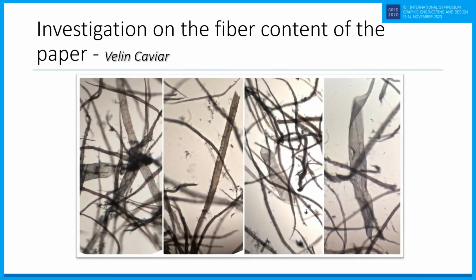On this figure is presented the microscopic analysis of Velin Caviar paper. This is the paper with the largest variety of types of cellulose fiber materials used. It consists of about 10% natural cotton cellulose, 40% softwood cellulose of two wood types, spruce and pine, in a ratio 1:1, and hardwood cellulose from two species of wood, poplar and beech, again in a ratio 1:1, with a total content of 50%.